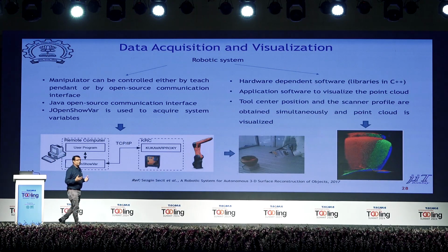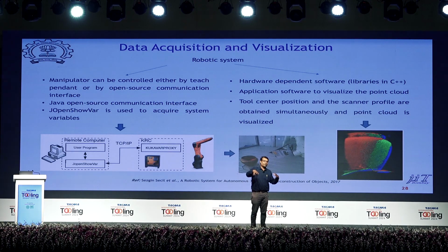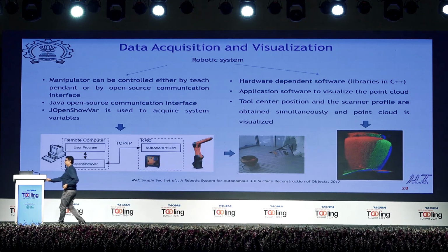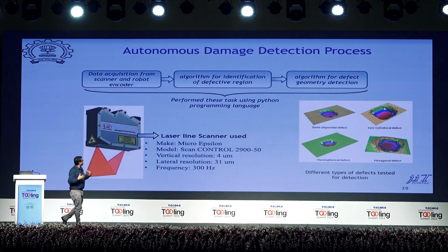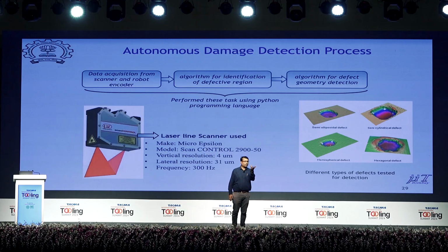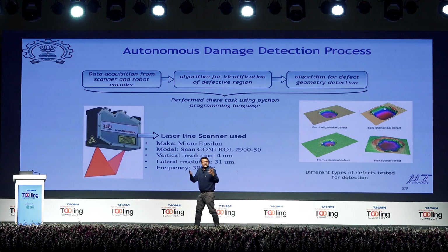Now the problem is that I also need to know where the defect is. If my mold is damaged, I should be able to do damage detection. So we use a laser scanner, get the data from the laser scanner and the robotic encoder, and fuse the information to create a 3D point cloud. From the data we also develop algorithms to do edge identification and identify what kind of geometry it is. We have been able to identify about 80 microns of defect. So that is our resolution. An 80 micron defect size I can easily detect, which should be more than required for any functional damage on the mold.